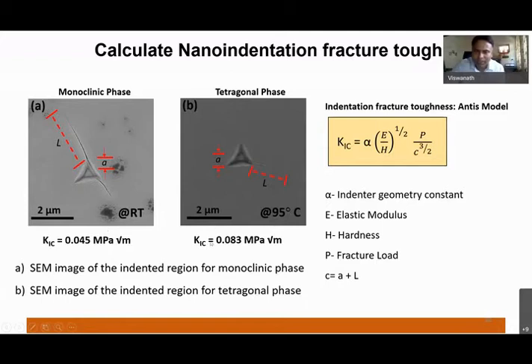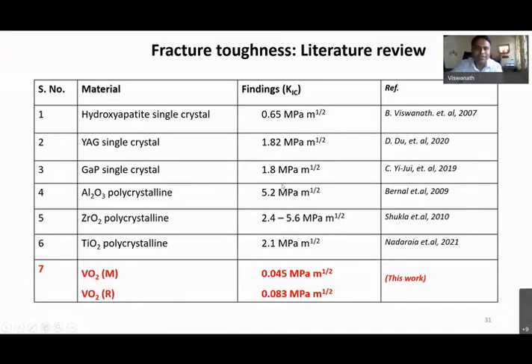There is a small jump, but anybody working in mechanical behavior would immediately dismiss such low values. I asked the second PhD student to continue and repeat it. Every time she probably gets a small change, maybe in the second decimal, but it does not come closer to the actual values that we expect for ceramics. If you look at other ceramics, typically it will be maybe 0.6 to 2-3 megapascal m to the power 1/2. So we are in no way close.